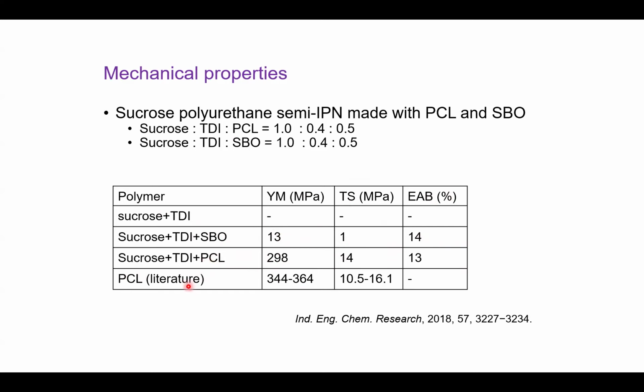And if you compare with the polycaprolactone by itself, you get very similar values, indicating that now polycaprolactone is fairly expensive, but sucrose is very cheap. And if you add this polyurethane to polycaprolactone, you can decrease the cost. So basically, you can get a lower cost, greener, biodegradable polyurethane. So this was published a few years back.